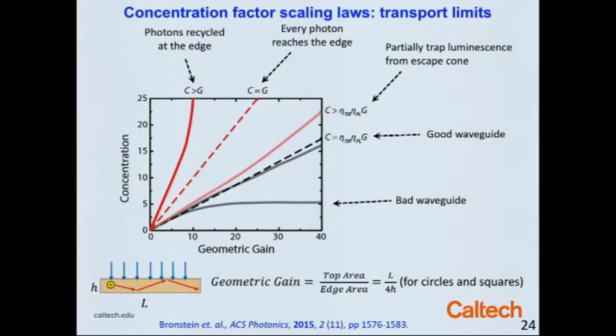So if we make one of these waveguides with quantum dots in it, the quantum dots absorb light and then emit luminescence photons. But we know total internal reflection can happen, and at angles smaller than the angle for total internal reflection inside a glass or polymer, some of the light would escape. If that happens, we lose some photons and that degrades our concentration factor.